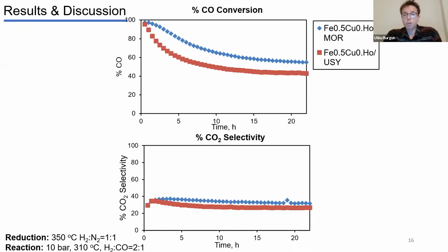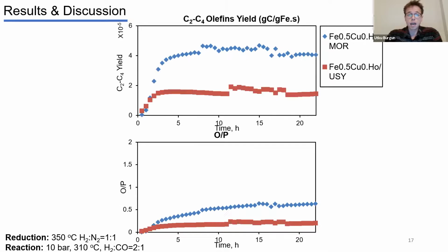Looking at the holmium promoted catalyst, the CO conversion stayed higher on the mordenite support than the ultra-stable Y, but here the carbon dioxide selectivity decreased slightly and came closer to the ultra-stable Y supported catalyst. And also the C2-C4 light olefins yield and olefin-paraffin ratio showed higher performance than the ultra-stable Y supported catalyst.